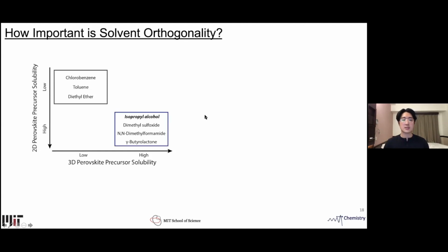The solvents listed in this blue box are often used to prepare the perovskite precursor solution because they have a high solubility. We discovered that isopropyl alcohol is uniquely positioned: it has low solubility against the 3D perovskite, but high solubility against the 2D perovskite precursor. This trend generally follows the increase in polarity.